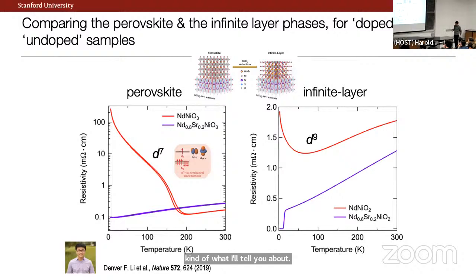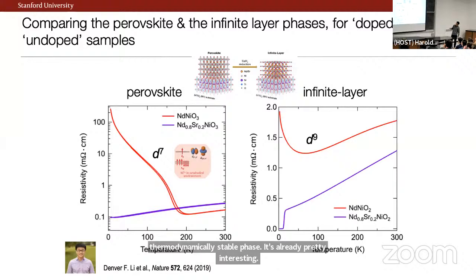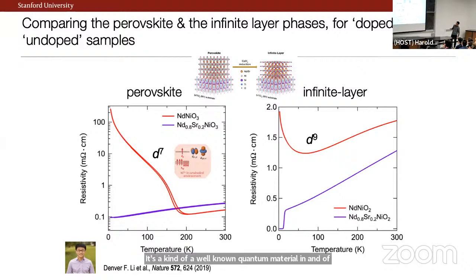Okay, so the first story is after these materials development, we could finally confidently understand and publish a statement of the basic phenomenology. It's quite interesting. Again, we start with the thermodynamically stable phase. It's already pretty interesting. It's a kind of a well-known quantum material in and of itself. So in this particular case, this perovskite nickelate again manifests strong electron interactions by going through this very big metal to insulator transition, where the insulating state is again characterized by a magnetic and orbitally ordered ground state. And it turns out that if you hole dope that lattice, again, you can suppress this ordering and make a metallic state, like the story I told you earlier.